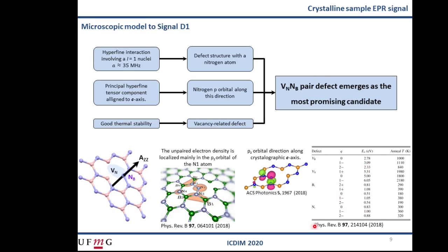For example, in this work, this PRB, there are several annealing temperatures for several defects, and the vacancy types are the most stable. It is useful to remember that this pair defect, the VNNB, is until this moment pointed out as responsible for the single photon emission at 1.95 electron volts in hBN samples. So the EPR data presented in this work could bring new insights on the physical properties of this defect.